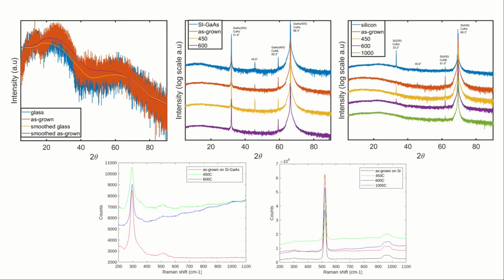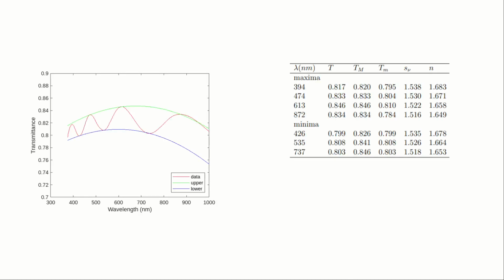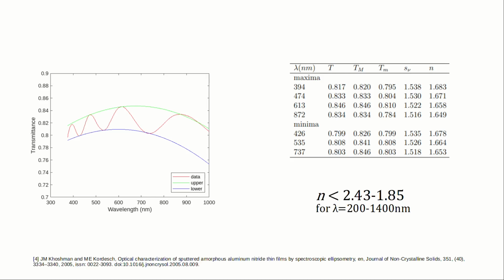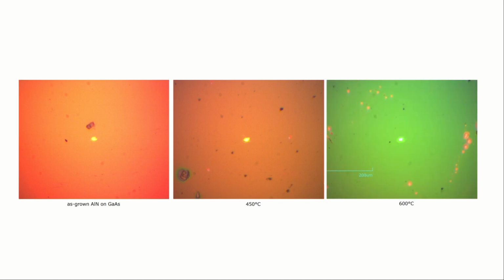The XRD patterns and Raman spectra of the aluminum nitride films indicate that the as-grown films are amorphous, and even after annealing at higher temperatures they remain amorphous. Refractive indices calculated from UV-vis spectroscopy data of as-grown films are lower than literature values, likely due to volumetric defects such as pores and cracks. This is supported by optical images of the thin film showing that defects in the material consolidate into visible regions as the annealing temperature increases.